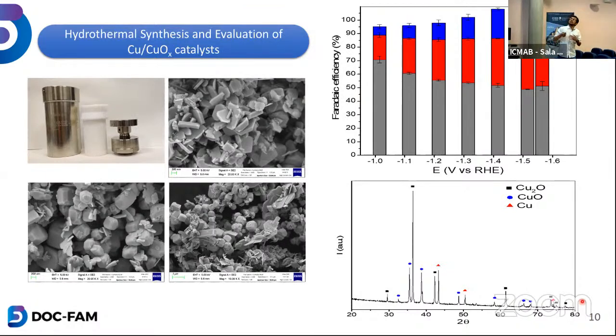But in this work, there has been a problem with the current densities. The current densities were not so high, because of course we need to have a better energy efficiency. The current densities have to be very high. So the higher the current densities, the lower the potentials, which is quite necessary for any mechanism like this.